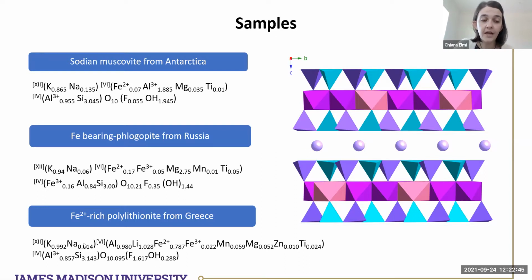And you see the potassium and sodium are in the interlayer. All of these substitutions for aluminum are in the octahedral layer. And the aluminum is also substituting silicon in the tetrahedral layer. And then you have oxygen, fluorine, and OH as anions in the structure to balance everything. So these big formulas collect the crystal chemistry and put together the information specific for the sample that we study.